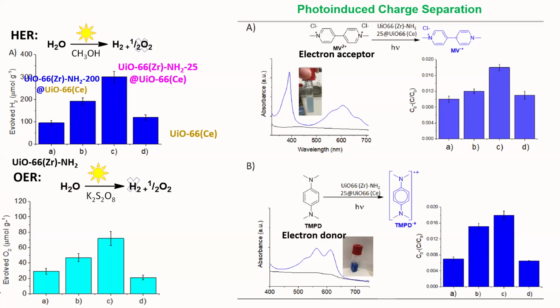And in the previous slide I showed the results of overall water splitting, and here we performed the individual activity, that is, this is for hydrogen evolution reaction, and this is for oxygen evolution reaction, and again we achieved a similar trend. So the best sample was UiO-66 zirconium amino 25 as a core, surrounded by UiO-66 cerium as a shell, so a MOF-on-MOF solid, and this was the most active photocatalyst for overall water splitting, as well as for hydrogen evolution reaction, as well as for oxygen evolution reaction.